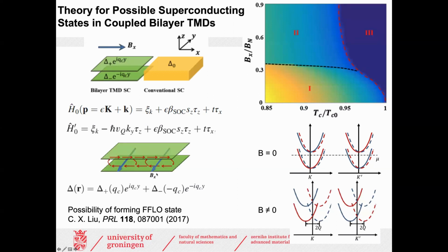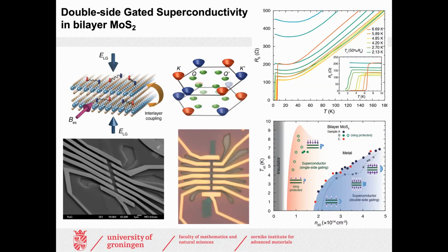And by applying B field, we add up one more term to the kinetic energy. And then we can actually form a coupled superconducting state. So namely, we have two layers over here. If you apply B field, they get split in the K space, and then you can have a couple pairing between these two K and K prime with this couple splitted band. And if you analyze this superconducting state, there's a possibility of forming FFLO state.